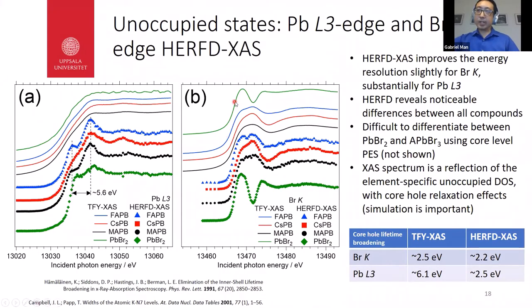So for TFY it is roughly 2.5 eV, and for HERFD it is 2.2. But it's still really helpful, because in the case of formamidinium lead bromide, when we look at the TFY spectrum, it's hard to say whether there are maybe two distributions of states. With the HERFD spectrum, we can really see that there are indeed two distributions of states.